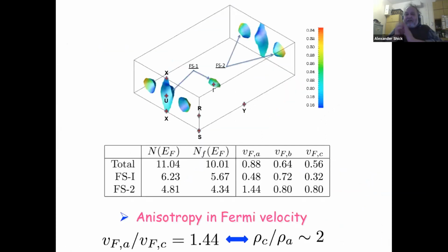So if you look at the Fermi surface, because it's a semi-metal with very narrow flat F-bands near the Fermi edge, the Fermi surfaces look like this with some small pieces of the holes and the electrons. And altogether, they indeed compensate each other. If you look at the densities of states from each of those pieces, you see that most of the density of states is an F electron density of states.